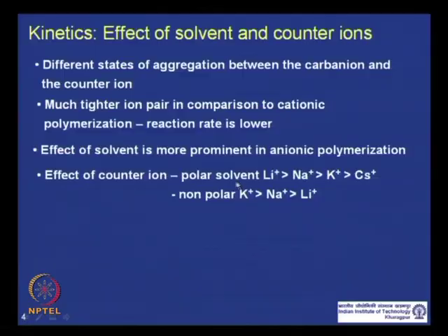Now, in the case of a nonpolar solvent, where the carbanion and the counter ion are tight, if the size is higher, the ions are a little loose. So, the reaction rate is higher. So, in a polar solvent, for a given anion, lithium cation will have a higher reactivity than sodium, potassium and cesium, and in a non-polar medium the order would be reversed.